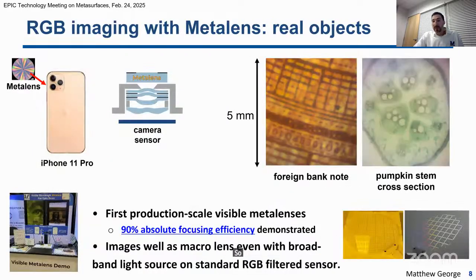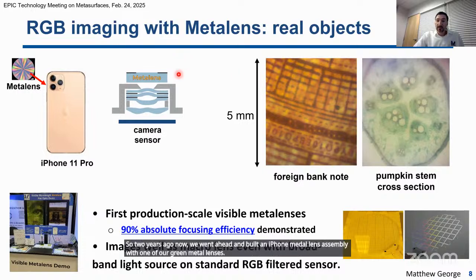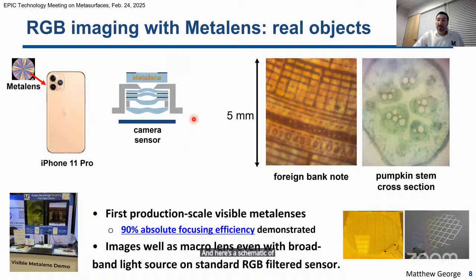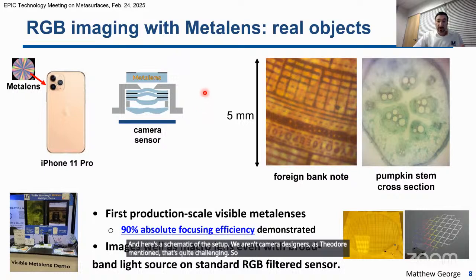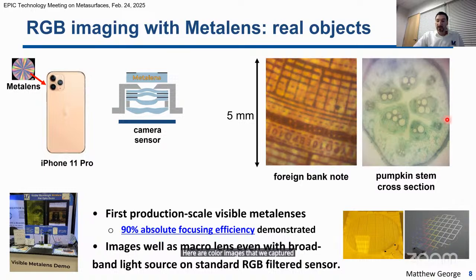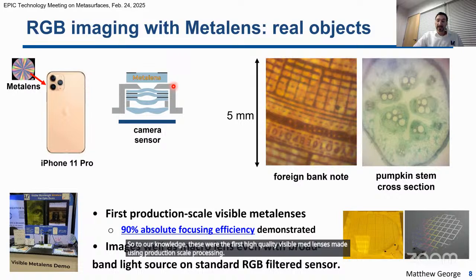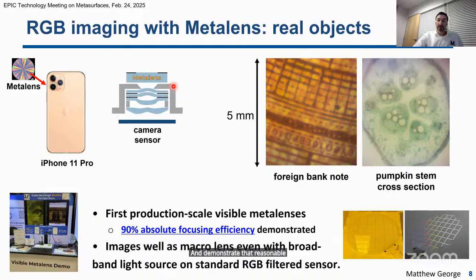So 2 years ago now, we went ahead and built an iPhone metalens assembly with one of our green metalenses. And here's a schematic of the setup. We aren't camera designers, as Theodore mentioned, that's quite challenging. So essentially, we just slapped our Metalens on top of the iPhone camera and used it as a simple macro lens for magnification of small features. Here are color images that we captured of a foreign banknote and the cross-section of a pumpkin stem. So to our knowledge, these were the first high-quality visible metalenses made using production scale processing, and demonstrate that reasonable image quality can be achieved when using metalenses, even with traditional RGB filtered sensor.